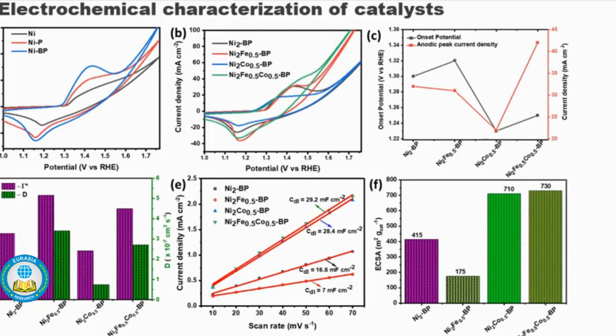The electro-oxidation behavior of the prepared catalyst was studied using cyclic voltammetry in 1 molar potassium hydroxide solution at 50 mV/s scan rate. The representative CV curves exhibited well-defined redox peaks during anodic and cathodic scans, corresponding to the nickel 2 and nickel 3 redox pair. By comparing the activity of the nickel phosphorus and nickel phosphorus boron, it can be seen that the redox peak increases after adding phosphorus to the nickel catalyst and further increases after adding boron to the nickel phosphorus catalyst.